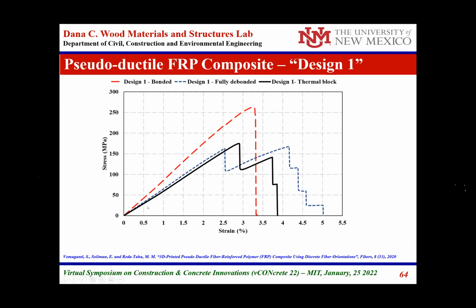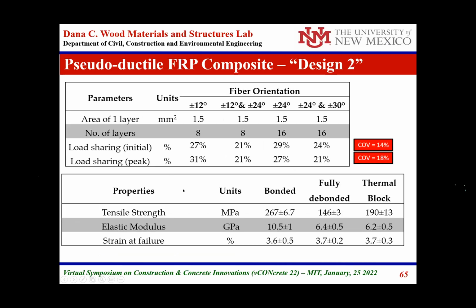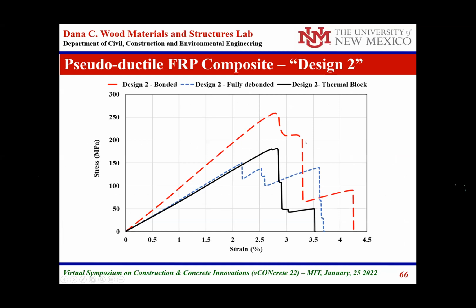And this is the testing of it. So this is the fully bonded material. You see, it does not have any ductility, but actually reaching 150, you can start getting some pseudo ductility here for the case of the fully debonded or the partially thermal block debonded. We changed the design and we actually got better results.